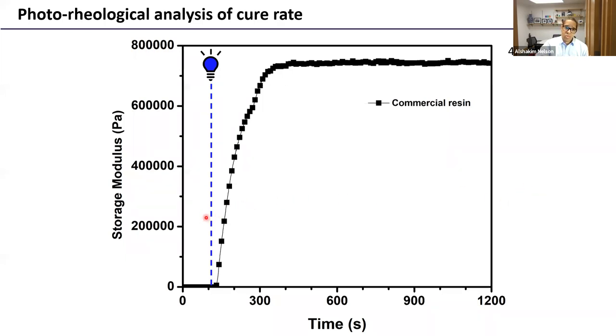Right, so we're looking at the change in storage modulus, which is essentially just saying the stiffness of the material, right? So we're going from liquid resin, and as this liquid resin cures, it's becoming stiff. So we can track that. And then we're tracking that over time after irradiation with light. And so this is just for a frame of reference here. This is just the commercially available resin for making a plastic using a Form 2 printer, okay? And so this is what that trace looks like.